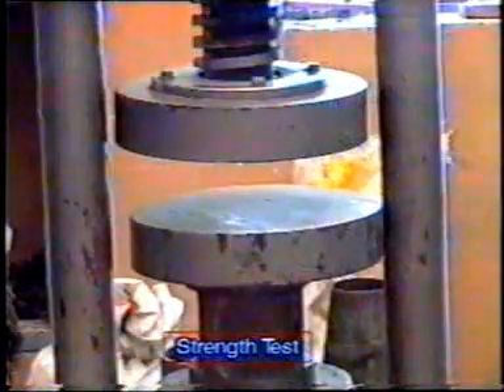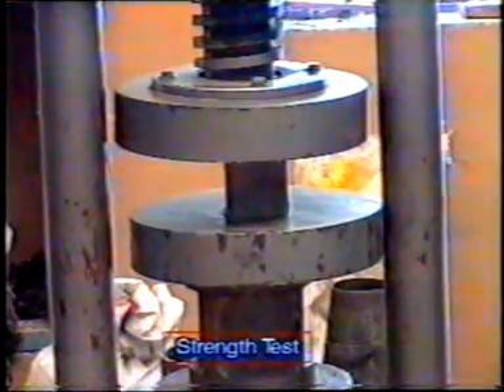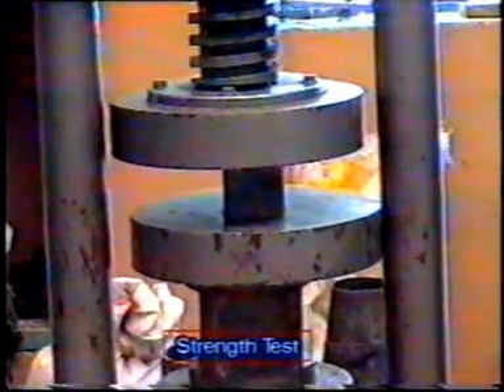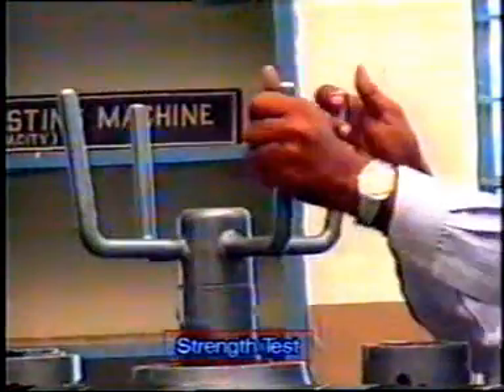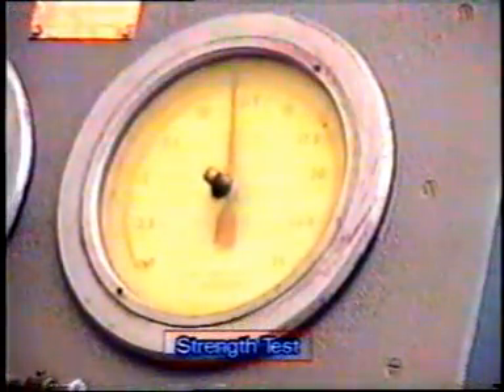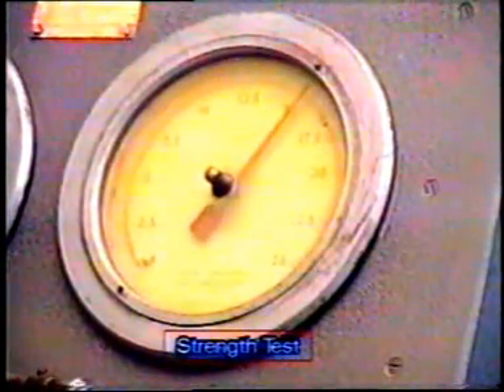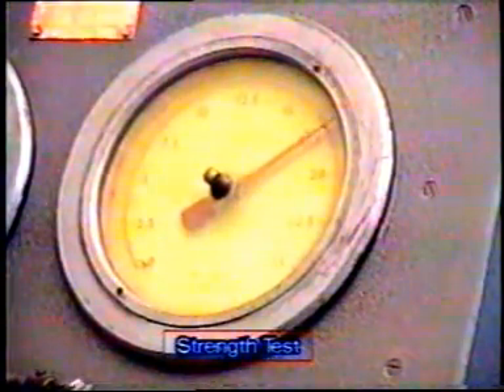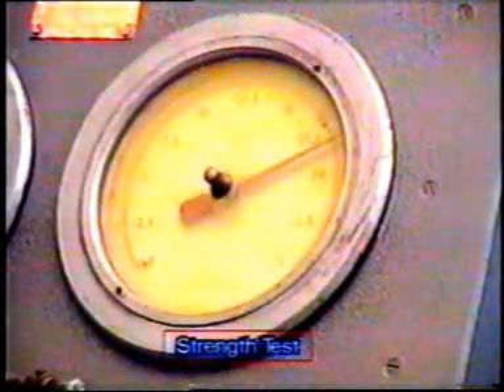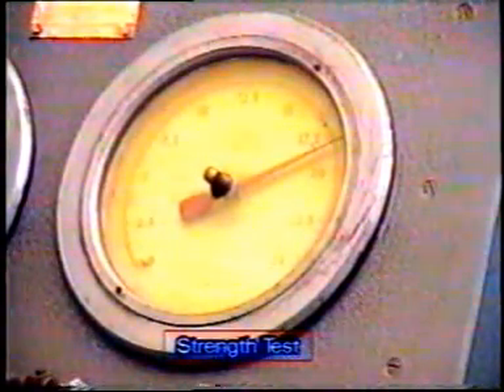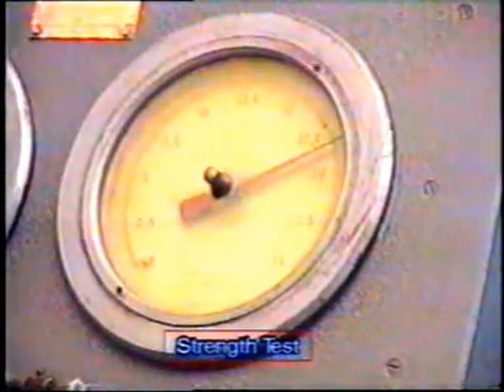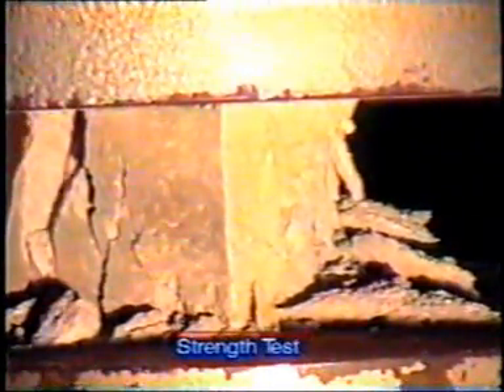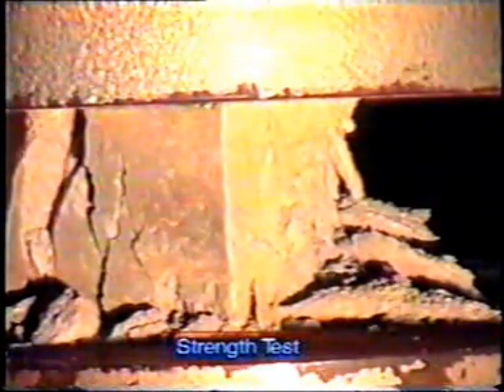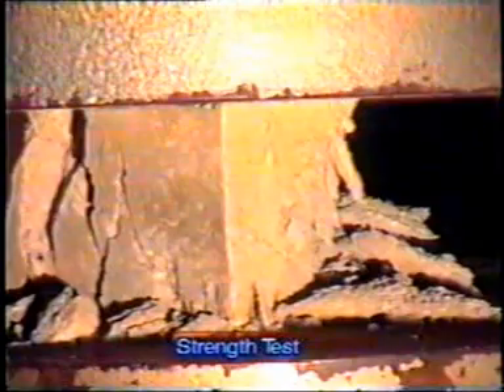Test the specimen in the compression testing machine by placing the cube in between the platens of the testing machine and apply the load at an uniform rate. Note down the load taken by the sample at its total failure. Load taken by the cube divided by area of the face of the cube which is in contact with the platens of the compression testing machine will be the compressive strength of the cement.